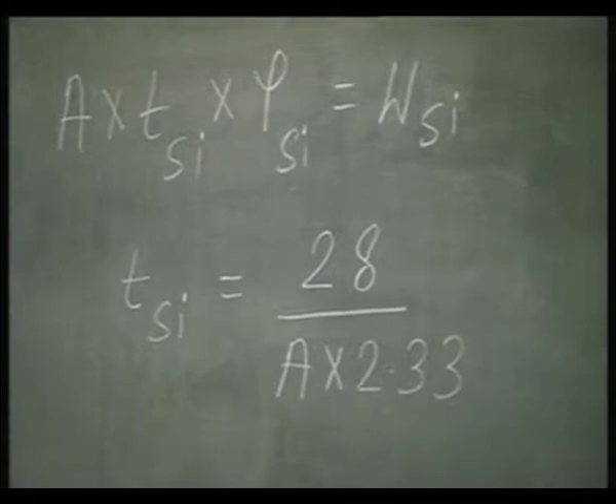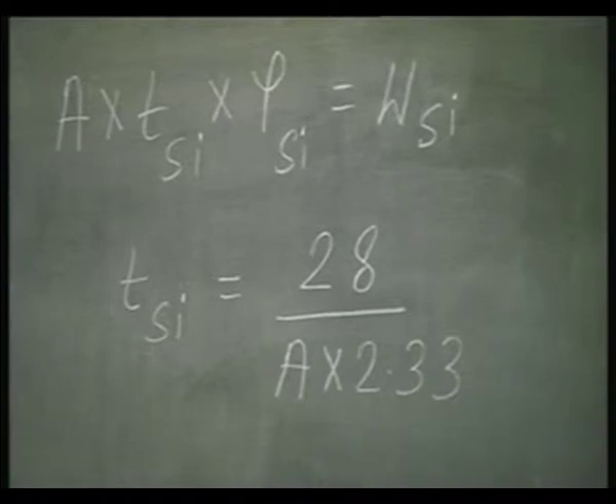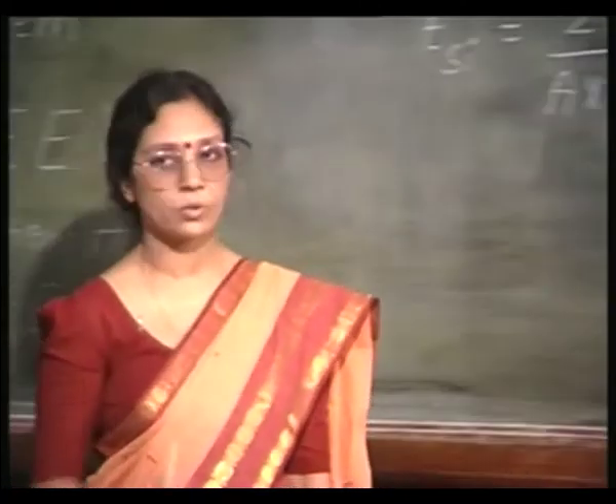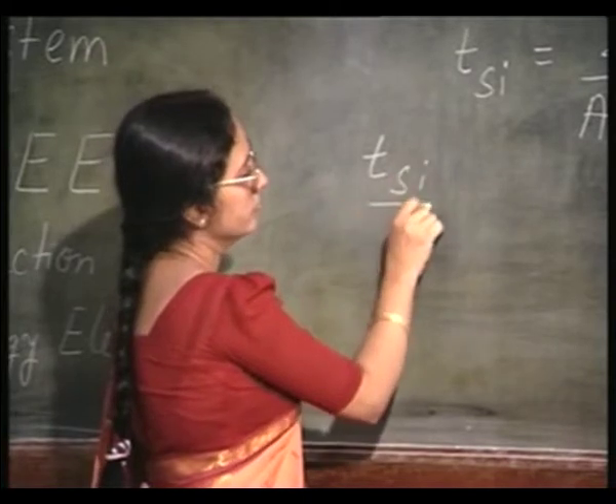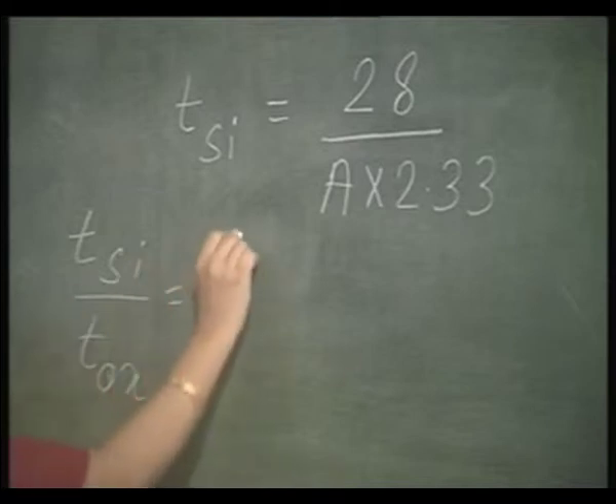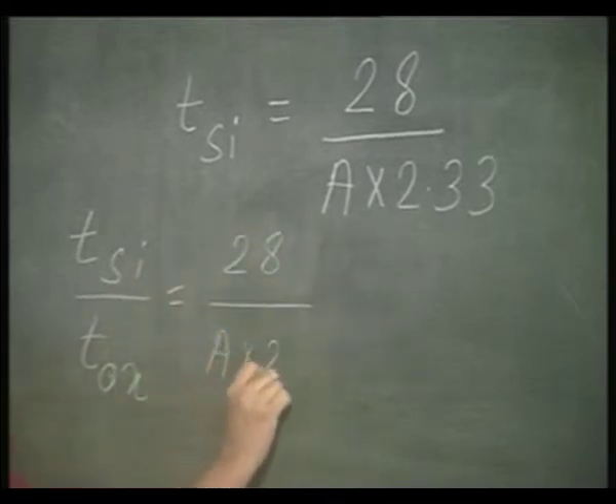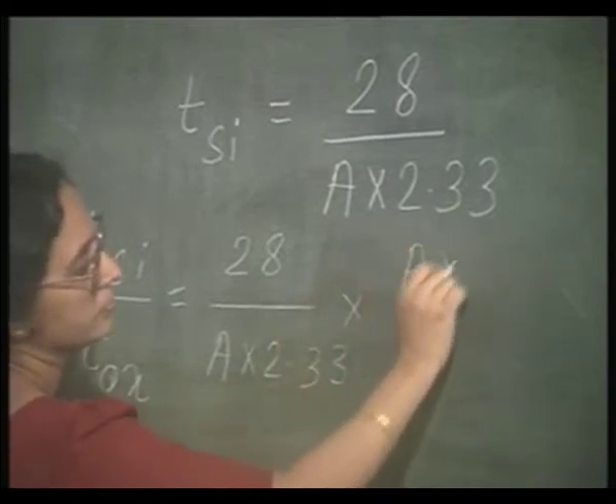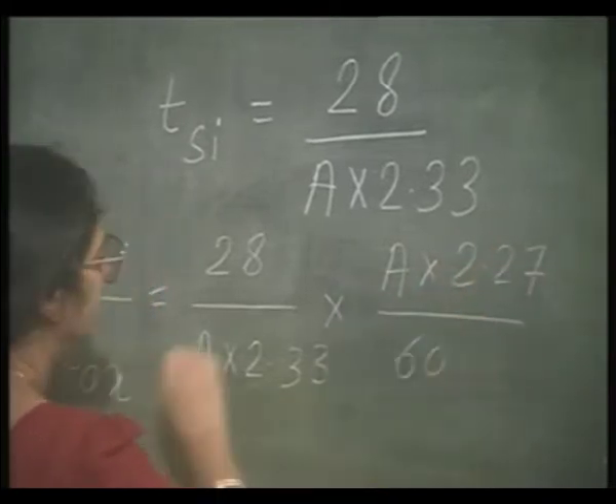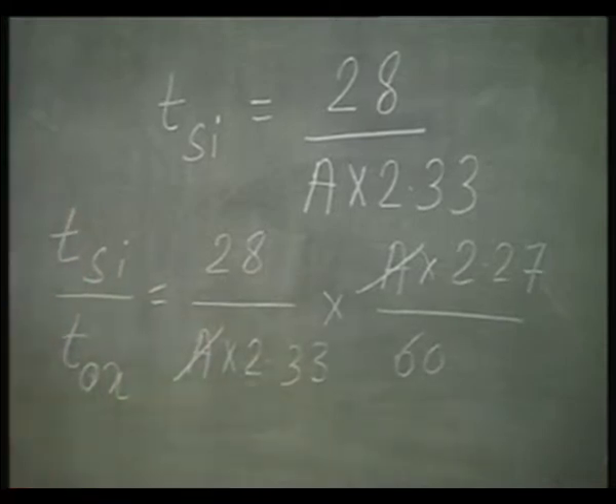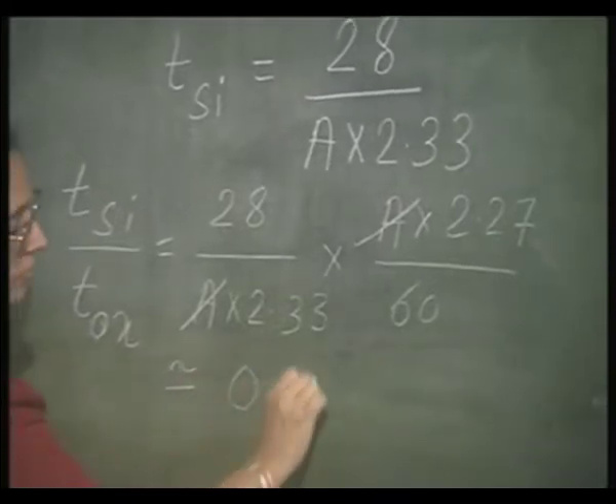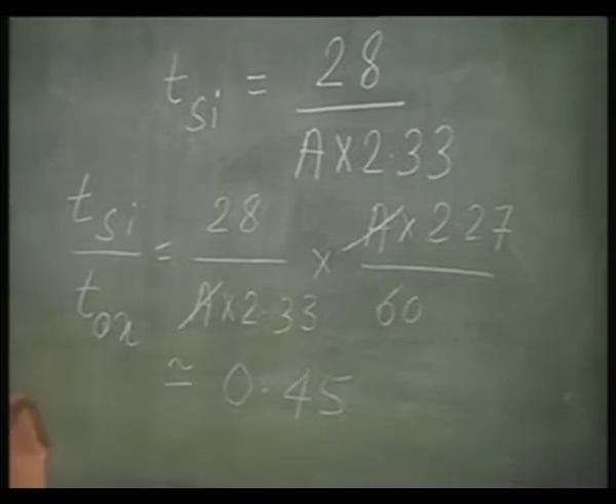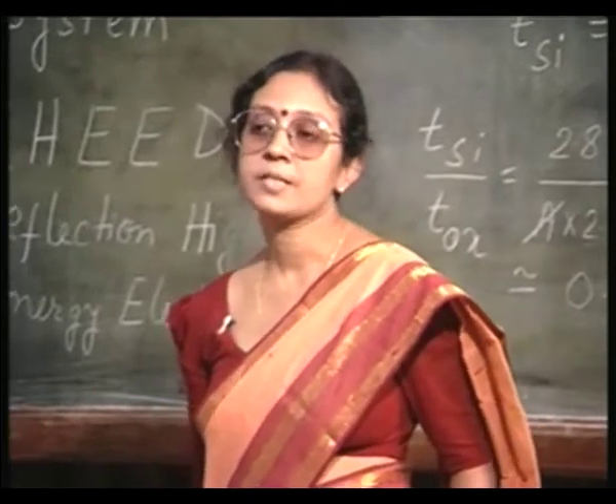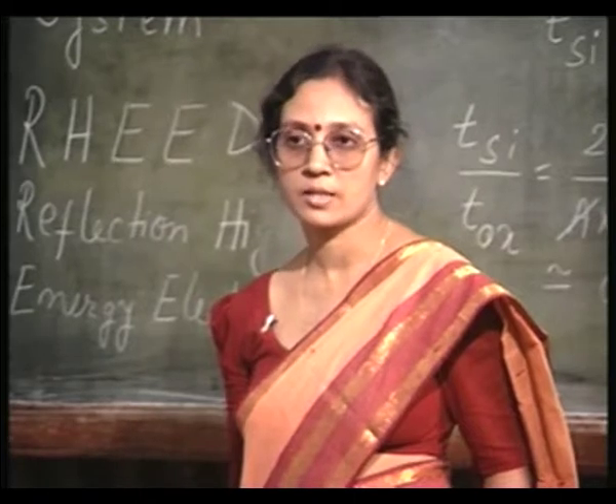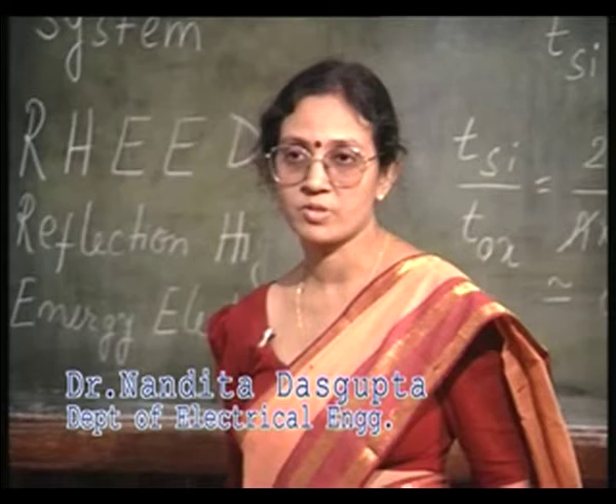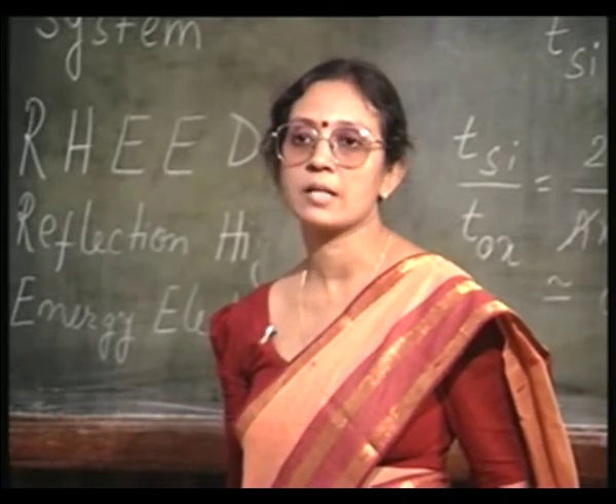So, now it becomes very simple. I have an expression for the silicon thickness that is consumed and I have an expression for the oxide thickness that is grown. So, you see, since they have the same cross sectional area, this works out to be about 0.45. What is the significance of this number? The significance is, if 1000 angstrom of silicon dioxide is grown, 0.1 micron, it has consumed 450 angstroms of silicon.